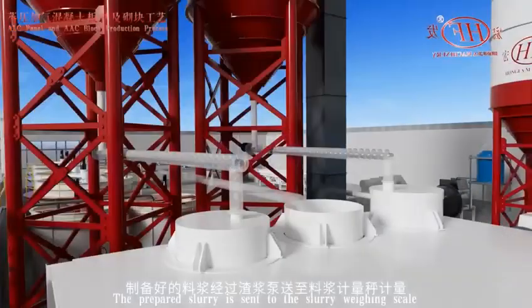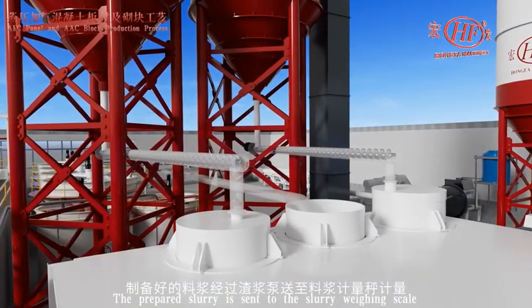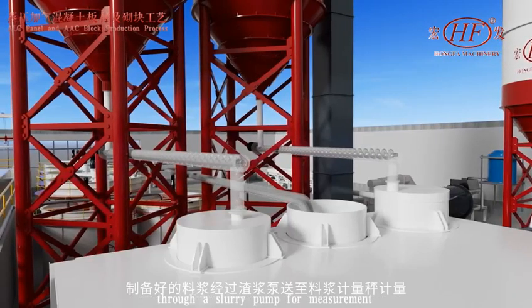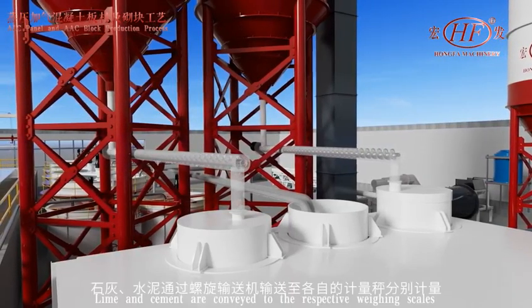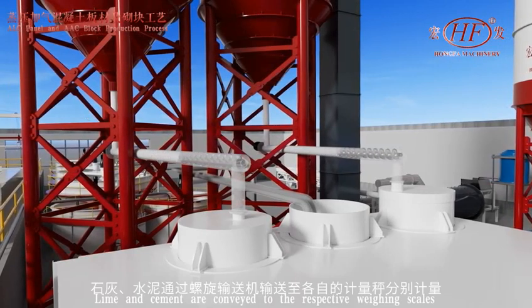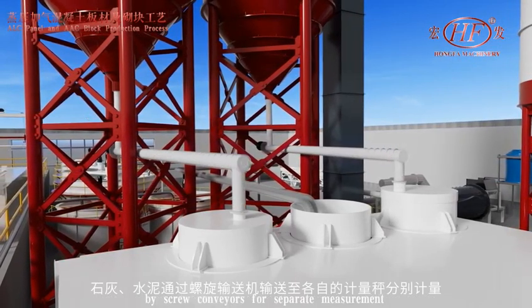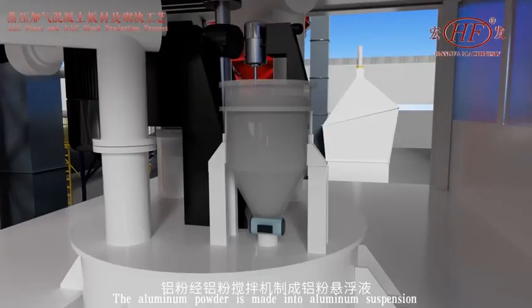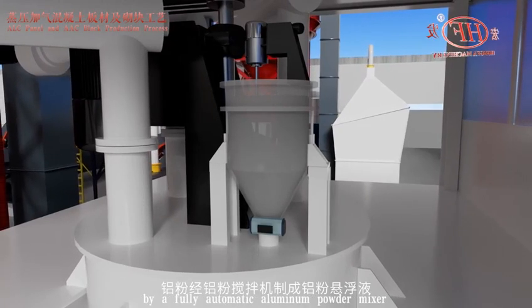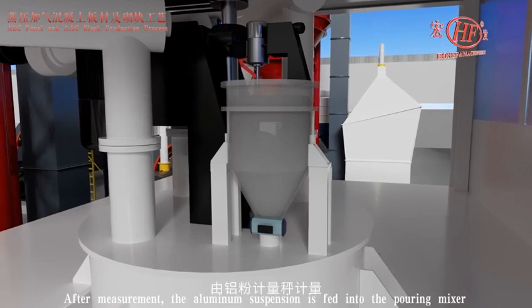3. Batching and pouring. The prepared slurry is sent to the slurry weighing scale through a slurry pump for measurement. Lime and cement are conveyed to the respective weighing scales by screw conveyors for separate measurement. The aluminum powder is made into aluminum suspension by a fully automatic aluminum powder mixer.